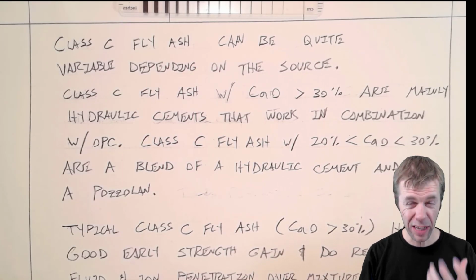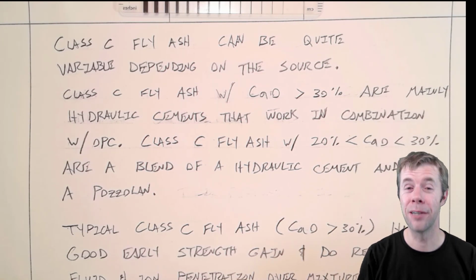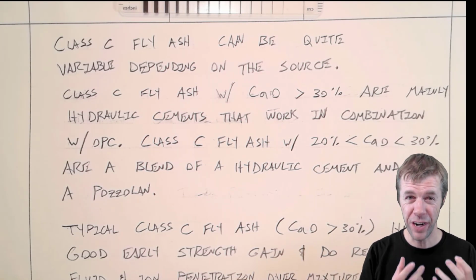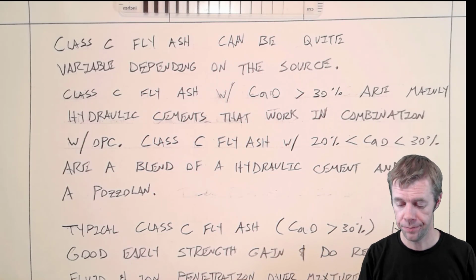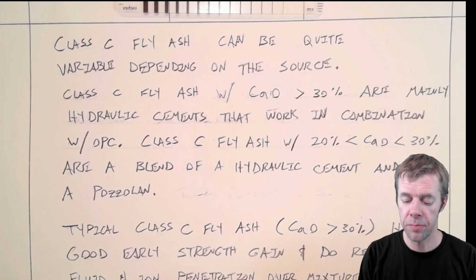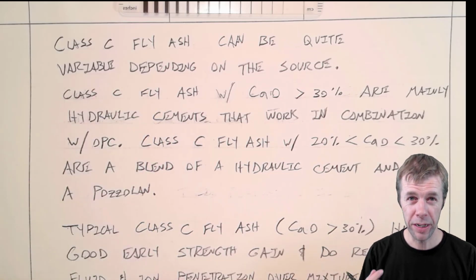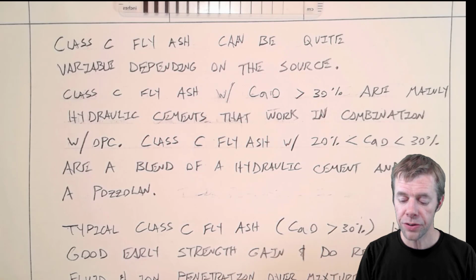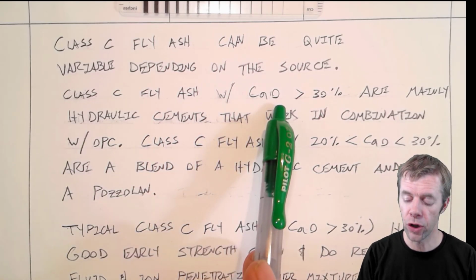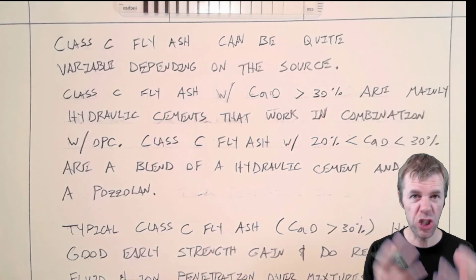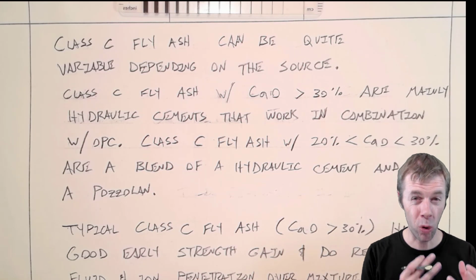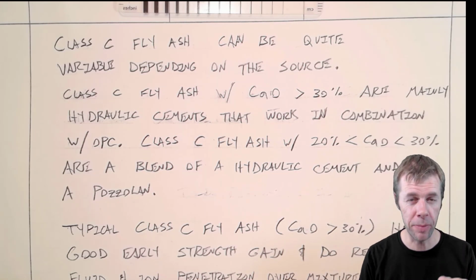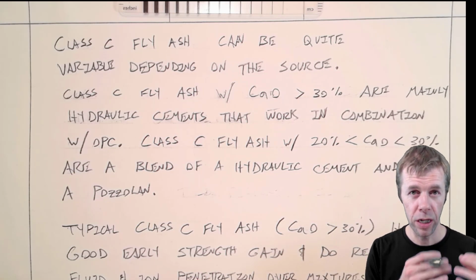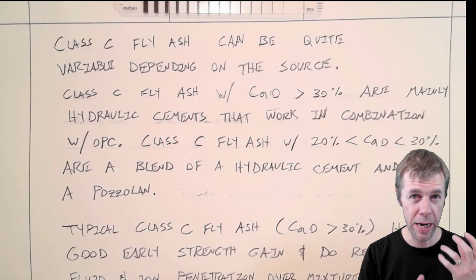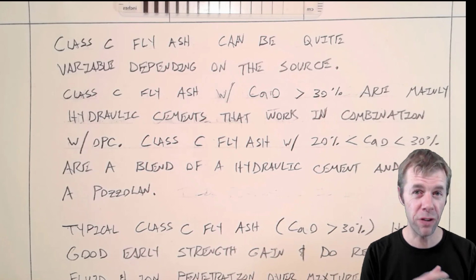Now let's talk about Class F fly ash's twin brother, Class C. They're very, very different from one another. Class C fly ash can be extremely variable depending on the source. Class C fly ashes with pretty high calcium oxide content, greater than 30%, they're mainly hydraulic cements. They're mainly just like a poor man's version of a Portland cement. They're usually activated by a Portland cement, as in the pore solution pH, the really caustic solution made by the Portland cement actually causes the fly ash to react.